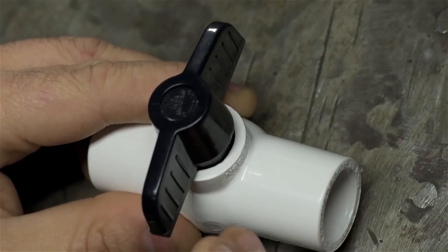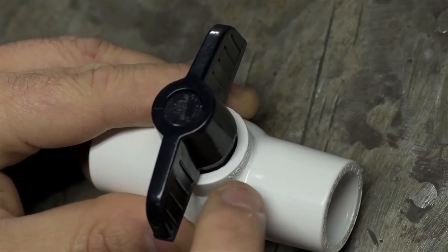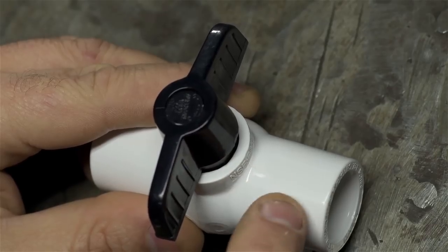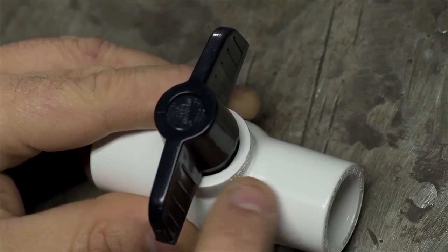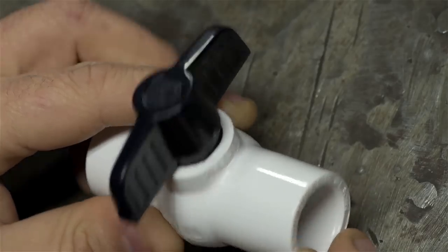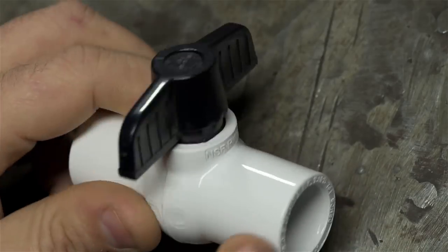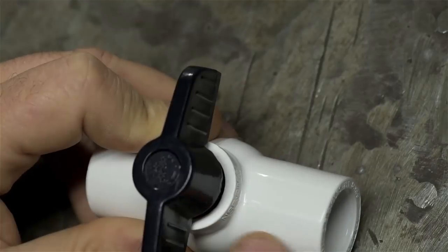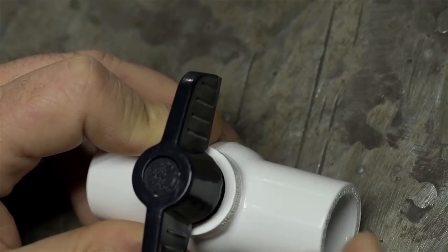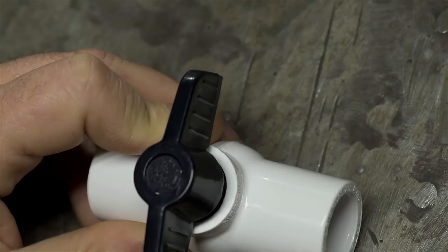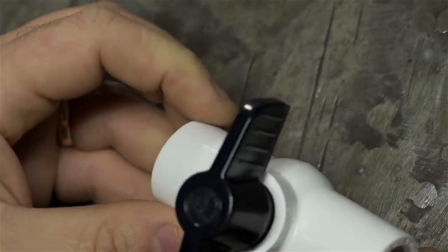Now, it's not a big deal here because this is PVC. But in some materials, that weld line could be a weak point. The material doesn't have the same properties there than it does in the rest of the part. Basically, if you were to smack this cylindrical area with a hammer, odds are pretty high that no matter where you hit it, that's where it would crack. Sometimes those can also be problematic from like a cosmetic standpoint. You don't want to make a part and see a big weld line running across the front of it. But again, in this case, I don't think anybody really cares. Although, and this is personal preference, I've bondoed, sanded, primered, and repainted all of my water valves.